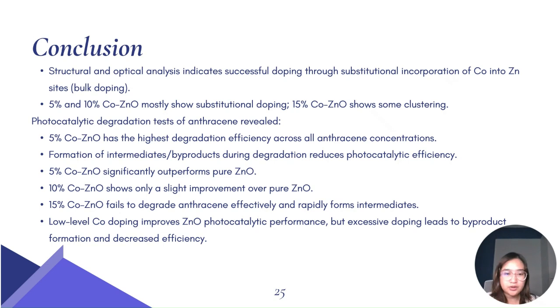To conclude, the structural and optical analysis indicates successful doping through substitutional incorporation of cobalt into zinc sites, which is bulk doping. The 5% and 10% mostly show substitutional doping, but the 15% co-ZnO shows some clustering. The photocatalytic degradation tests of anthracene revealed that 5% co-ZnO has the highest degradation efficiency across all anthracene concentrations. The formation of intermediates and byproducts during degradation reduces photocatalytic efficiency. The 5% co-ZnO significantly outperforms pure zinc oxide. 10% co-zinc oxide shows only a slight improvement over pure zinc oxide. 15% co-ZnO fails to degrade anthracene effectively and rapidly forms intermediates. Low-level cobalt doping improves the zinc oxide photocatalytic performance, but excessive doping leads to byproduct formation and decreased efficiency.